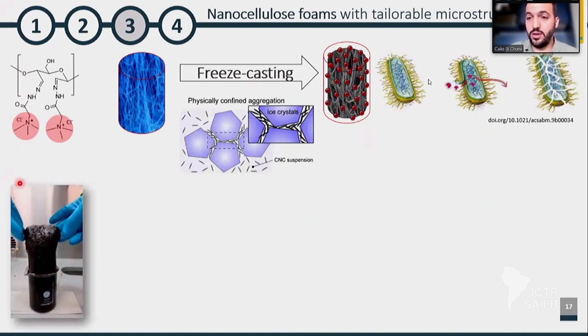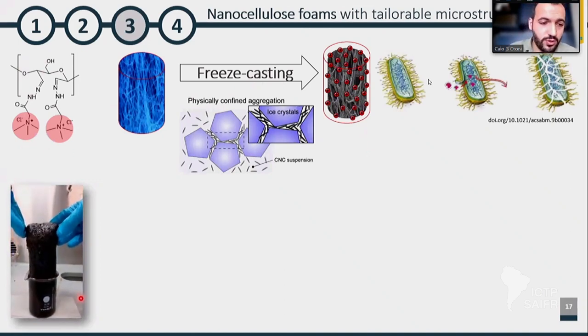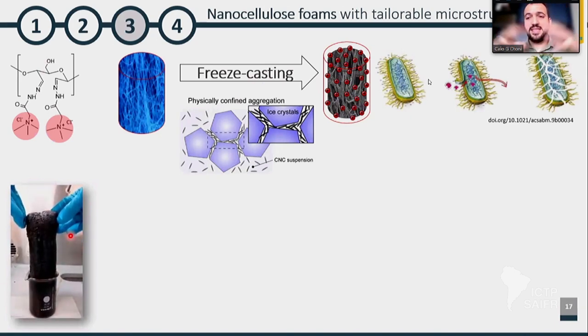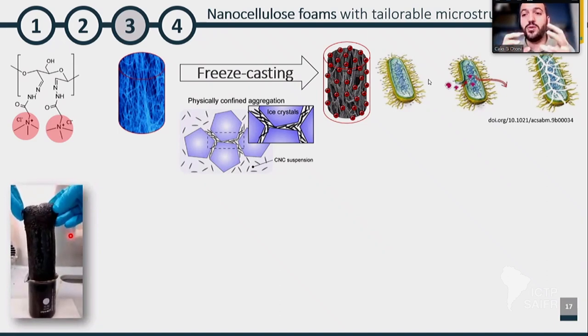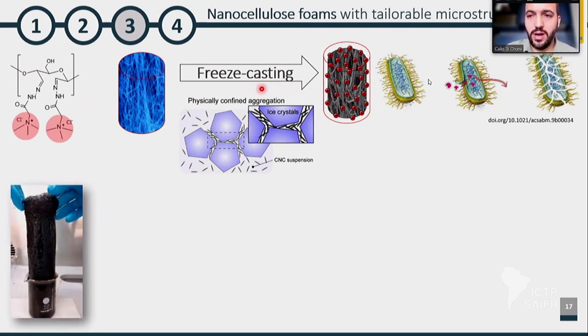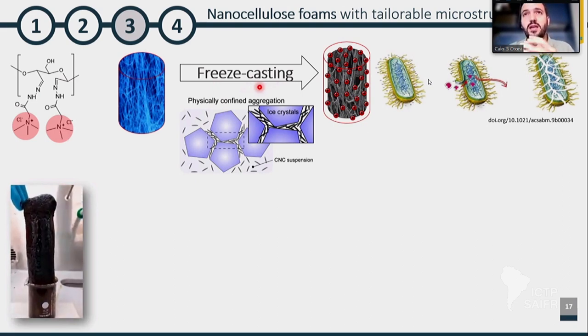The third example that I would like to give is still in cationic cellulose, but in solid material, usually foams. So we have different procedures to produce these foams. This is a self-condensation reaction that expands the colloidal suspension, and we then quench, we then cross-link and maintain the structure. The other is what we call cryo templating. So we freeze cast and use ice as a sacrificial template because ice grows,